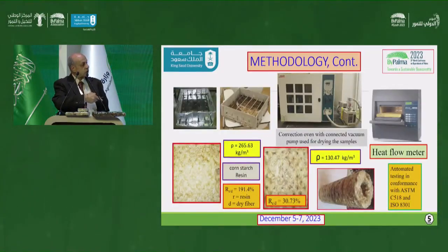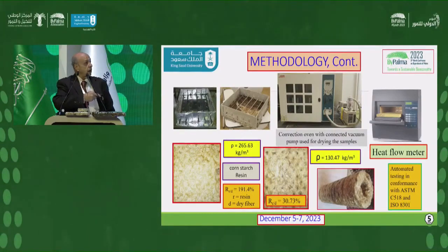This is how the process goes. We collect the fibers, and this is the mold. We put it in the mold, okay, press it, and then move it to the oven, and after it is completely dry, we move it to the heat flow meter to measure the thermal conductivity. And these are some samples made only from the palm tree surface fiber, just as a little introduction, okay? And we can make it in a cylindrical shape to roll it around any pipe or something like that, okay?